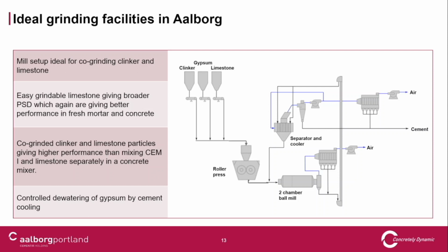With this setup, we are ready to make a limestone cement based on the white clinker. By this process, we also see an increased effect of the limestone compared to just adding limestone and cement separately — we get a good intimate mixing of the limestone particle and the clinker particle when we co-grind it instead of blending it.